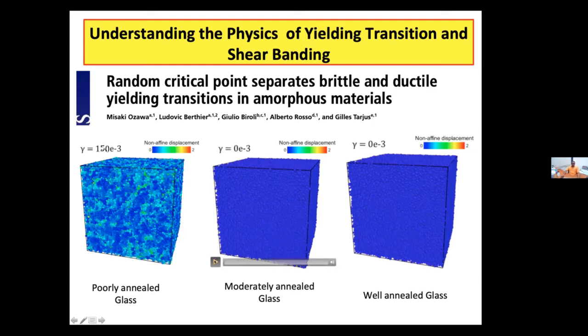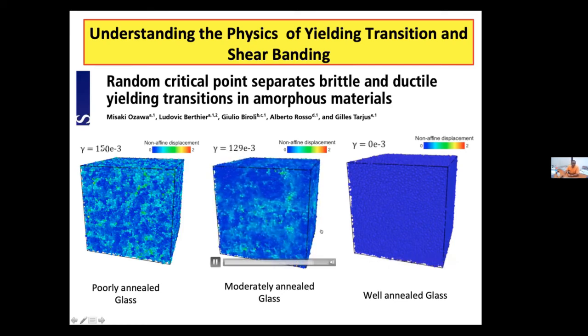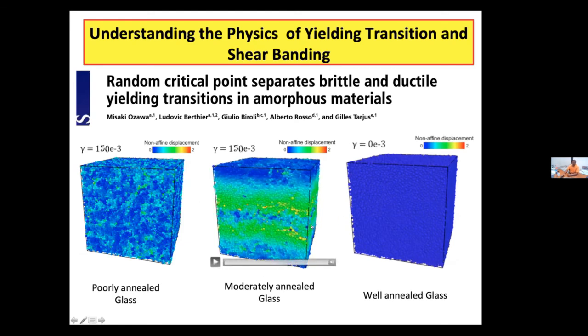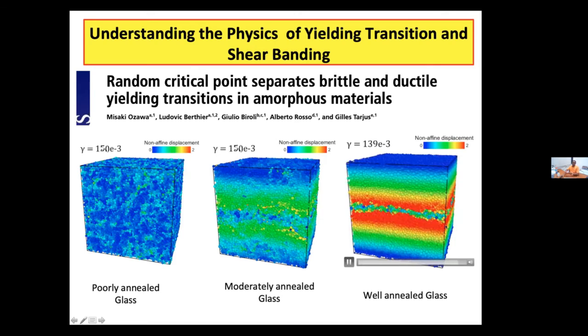So now you generate the glasses which are moderately annealed, and then you see a very different type of behavior. There is not much plasticity until you see a large region where the strain gets localized. And this is an indicator of shear band formation. So now if you look at the extremely well annealed glass obtained via Swap Monte Carlo, then the phenomenon becomes even clearer. You see that until the shear band formation, there is almost no plastic event. And then suddenly there is a slip.